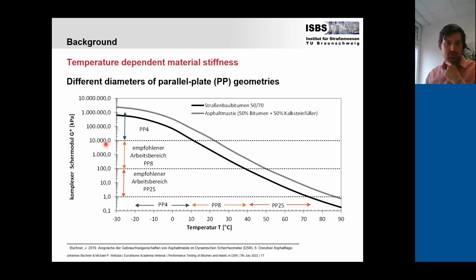And now just recently introduced into the current draft of the standard, the 4 millimeter geometry for these very low temperatures, 10 megapascal to 1 gigapascal. And you can see here, based on the stiffness curves, it's roughly these temperature ranges which are suitable for the different geometries: minus 20 to 10 for the 4 millimeter, 10 to 40 for 8 millimeter, and 40 to 70 for 25 millimeters. It changes a little bit depending on the stiffness. For mastic, you might need a little bit higher temperatures, but basically that's the background why we are using different geometries in the different temperature ranges, and divide all the testing in different temperature ranges.